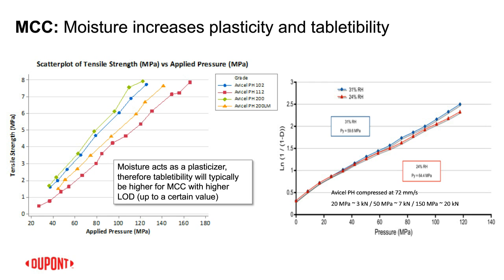Question for you. Obviously you were talking more about moisture, and the impact of moisture, low moisture grades versus non-low moisture grades. But I remember what you were talking about earlier in the presentation about the impacts of particle size. And at least within this regime, as you go from a PH 102 to a PH 200, it doesn't seem like you're seeing that much of a drop-off, if any at all, in compactibility between these two grades. Would that be a fair statement?